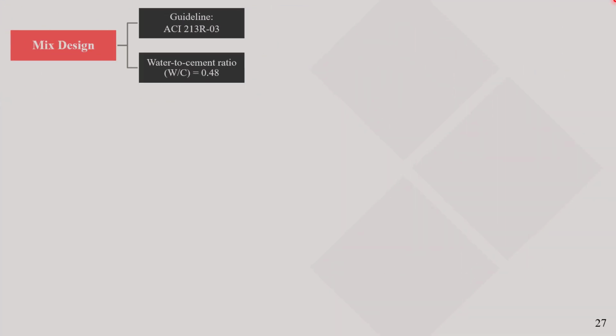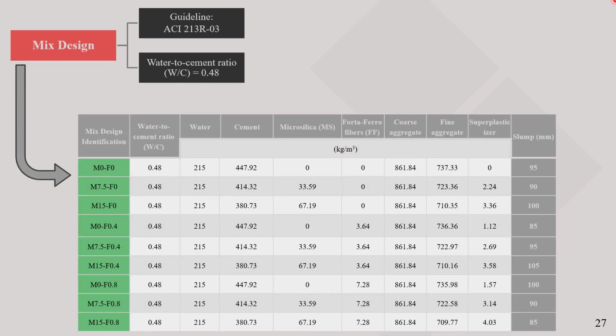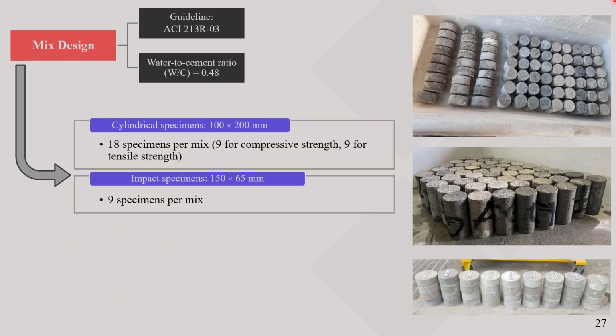Mix designs. The mixes were prepared with a fixed water-to-cement ratio of 0.48. The table includes 9 mix designs. The number for microsilica shows its percentage by weight. The number for Forta-Ferro fibers shows their volumetric percentage. For example, the sample M7.5F0.4 contains 7.5% microsilica by weight and 0.4% Forta-Ferro fibers by volume.